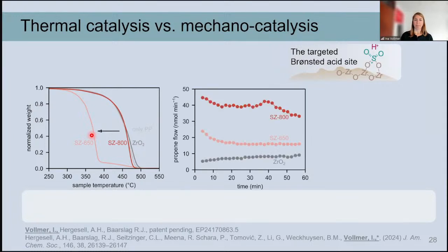And so then we used also another treatment at 800 degrees with the sulfuric acid, and this actually created absolutely no thermocatalytic activity. However, when we then use this in ball milling, which is what is shown here, you can see that the propene flow is a bit higher for this catalyst treated at 650 degrees, but it is even higher for the one treated at 800 degrees, which was not thermocatalytically active. So somehow there is a mismatch between what we see in thermocatalysis and what we see in mechanocatalysis.